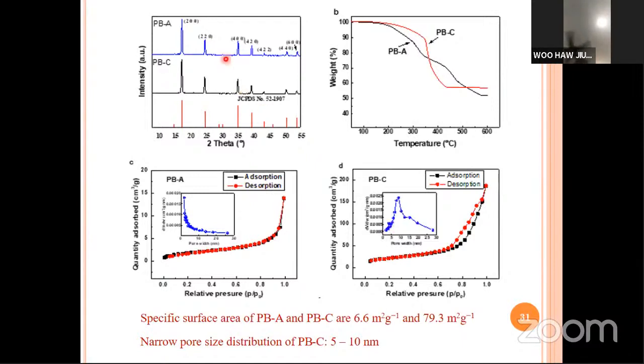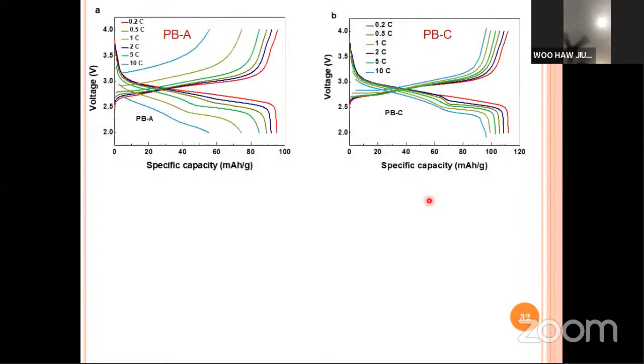Now this is the XRD diagram. Not much changes. All the sharp peaks are still there. This is the TGA result. This is the specific surface area for PB-A. Now, after etching, we are getting 6.6 meters square per gram. After etching with double heating, we are getting 79.3, and with very narrow pore size distribution here, between 5 to 10 nanometers. Therefore, of course, we can't wait to test the electrochemical performance.